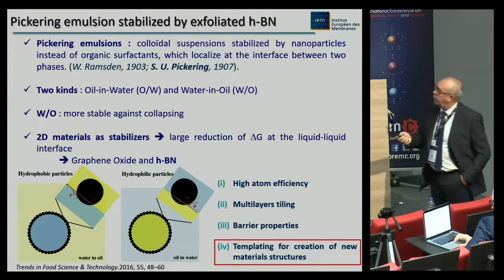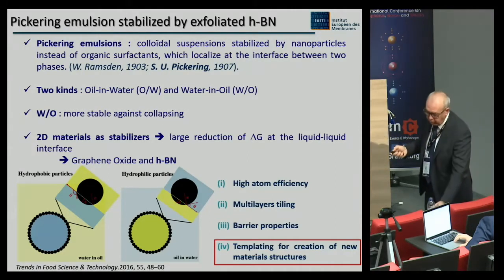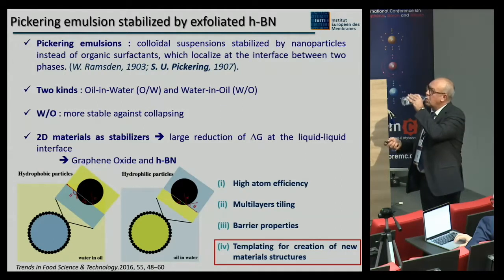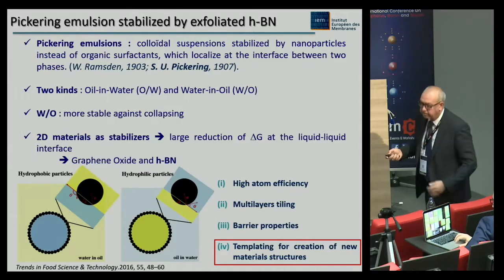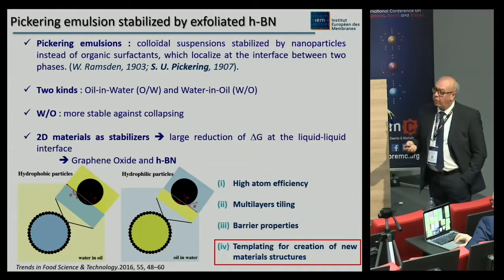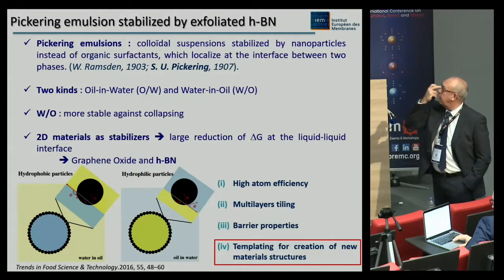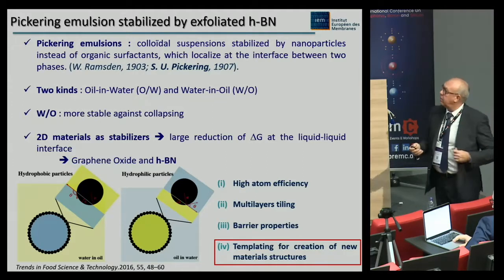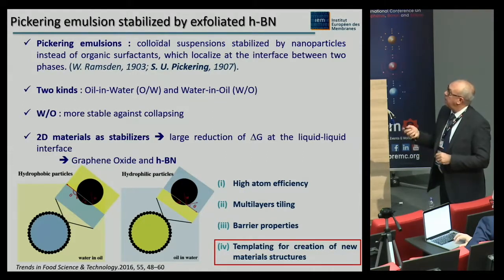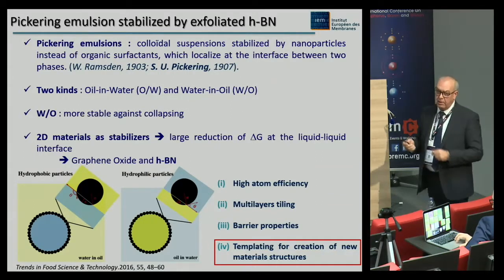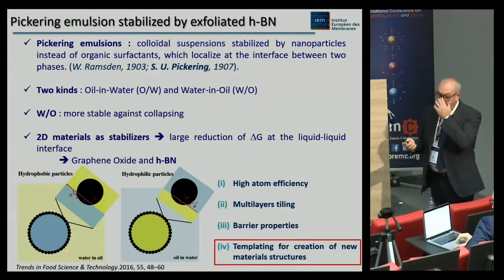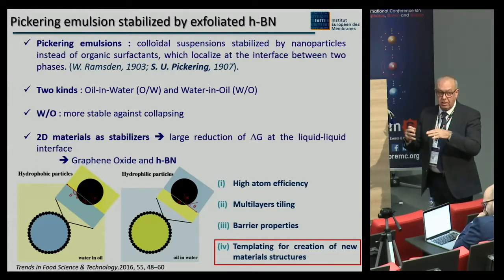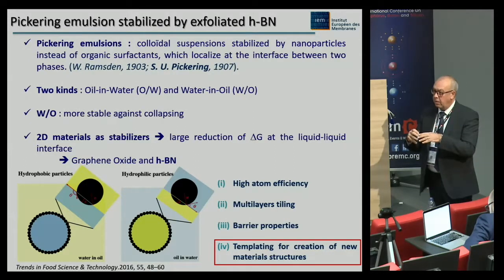So the last example for today is a very new study that we have started in the group with a PhD student. The idea is to use Pickering emulsions to prepare porous materials. Pickering emulsions are colloidal suspensions stabilized by nanoparticles instead of organic surfactants, and these particles are localized at the interface between the two phases. This was observed by Ramsden and discovered by Pickering a few years later, at the beginning of the 20th century. The interest of this emulsion is that the particles are completely stuck at the interface, meaning that you can obtain a very stable emulsion.